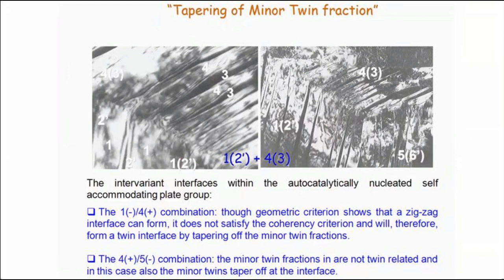And the general case, or a more general case, would be one in which the minor twin fraction is not twin related. And here is the evidence. And you see the minor twin fraction tapering away. And when they taper away, you're getting just a single interface where the major twin fraction is twin related. So this is the situation, and this is the evidence.